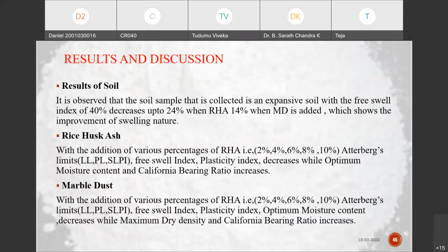Coming to the results and discussions, we can observe that the soil sample's free swell index decreases from 40% up to 24% with RHA 14% and when MD is added, which shows the improvement of swelling nature. And with rice husk ash, the liquid limit, plastic limit, shrinkage limit, and plasticity index decrease, while optimum moisture content and California bearing ratio increase.